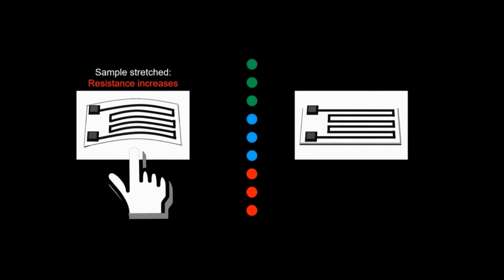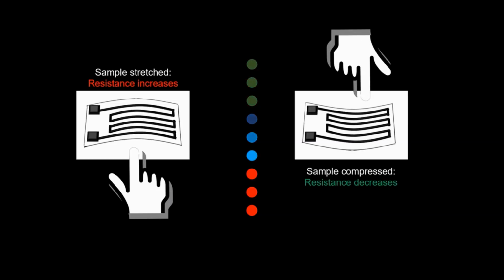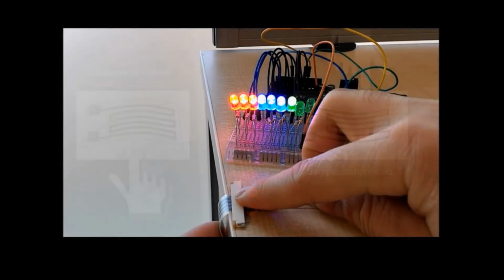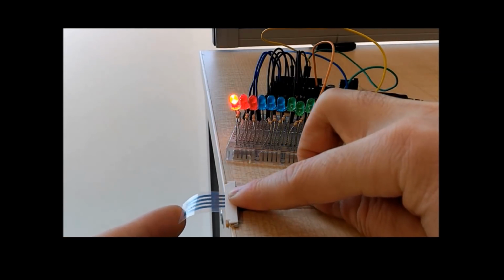So one of the applications we look at is simple strain sensing. So if you print a graphene resistive track, as you bend it one way, you're stretching the sample. If you bend the other way, you're compressing the sample. So essentially you can improve or decrease the conductivity of graphene just by bending it. So this is a simple demonstration.